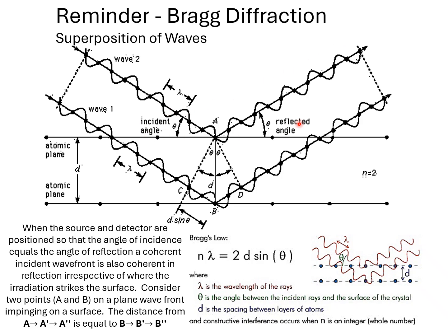In addition to that, if we look at waves that are scattered from atoms deeper within the crystal, there's a certain condition where you will get coherence, or if you like, strong superposition between the waves reflecting from the two different layers. You will get that condition where you get maximum superposition, and the maximum signal occurs at a specific angle.